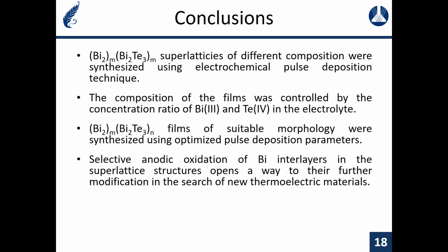Concluding my presentation, in this work we developed the electrochemical way of synthesis of layered superlattice structures with controllable composition composed of Bi2Te3 layers and bismuth bilayers building blocks. Verified their structures by X-ray diffraction, X-ray photoelectron spectroscopy and high-resolution transmission electron microscopy, and optimized the deposition process to produce films with good morphology required for thermoelectric applications. Additionally, we found out that selective anodic oxidation of bismuth bilayers and removal from the superlattice is possible and results in expanded bismuth telluride structure, which is of interest for introduction of other elements.